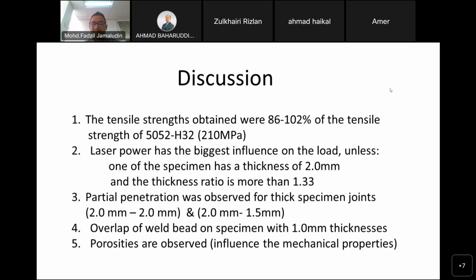And as for number 3, we have mentioned that partial penetration was observed for thick specimens, and for smaller specimens, 1 mm thicknesses, we can see that there's an overlapping of the weld bead, which is desirable. Unfortunately, porosities are observed, and this can influence the mechanical properties. For welding of aluminium, even when using other technologies, porosity cannot be avoided, but we try to minimize it. This will be another area that we can look into. Porosity is usually caused by entrapment of gases during solidification.